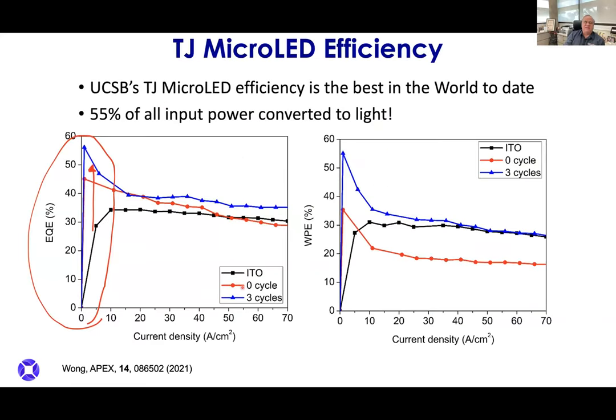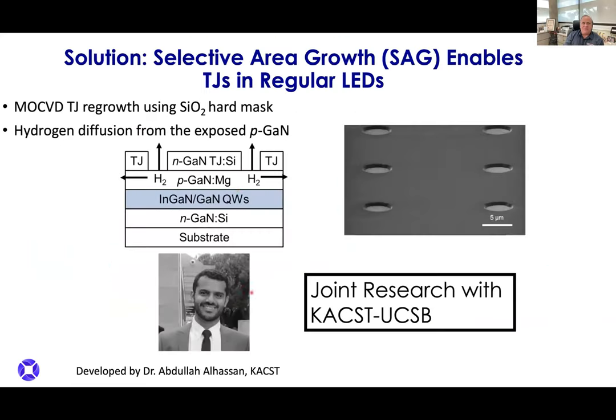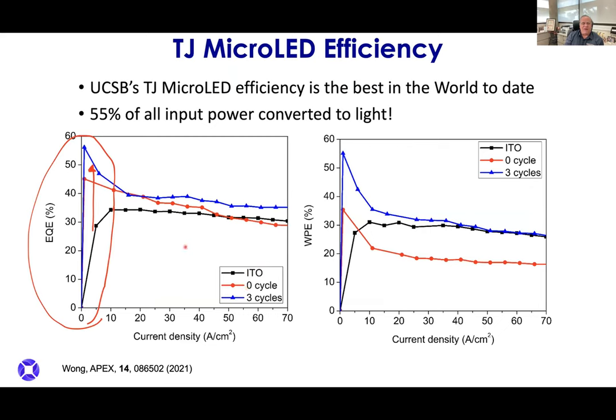Oh, so cycles is how many times we heat it up and take it through this thermal cycle to drive out the hydrogen. Because there's some space here that's still covered with N-type, you have to give the hydrogen time to diffuse up and out this hole. And so Matt Wong found out, yeah, zero cycles is good, it got you to this red line, but taking it up to three cycles, you can see we went from 35% to 55%.